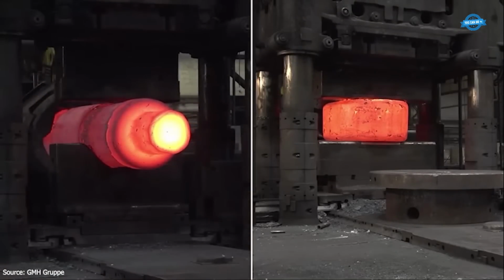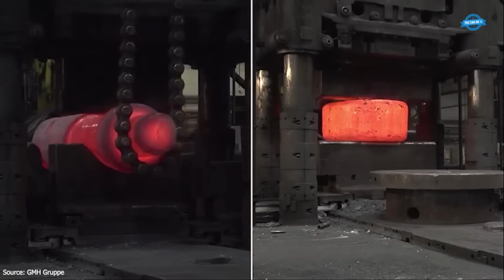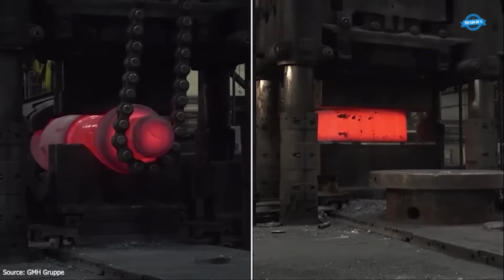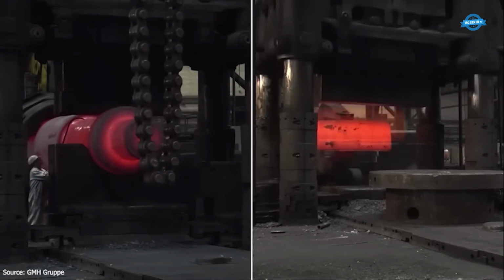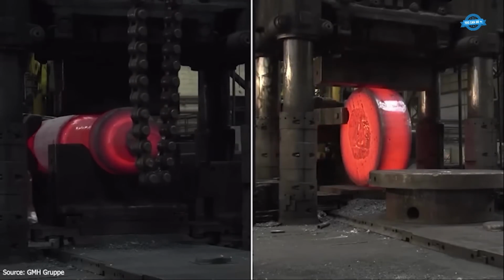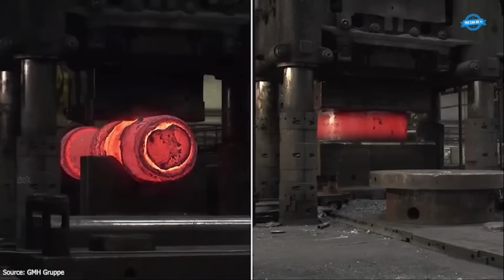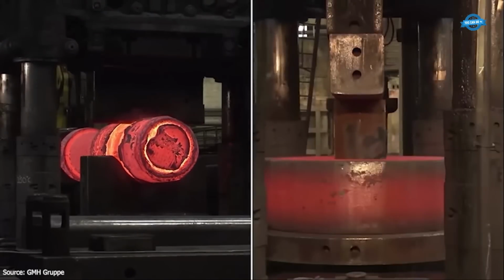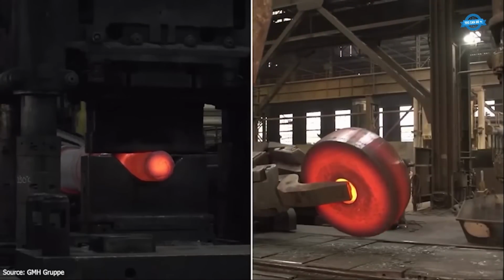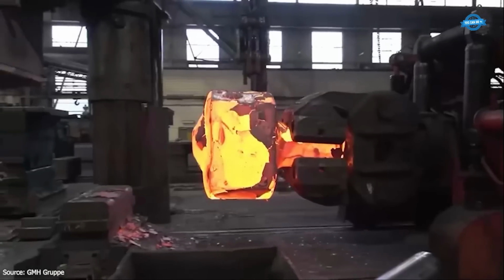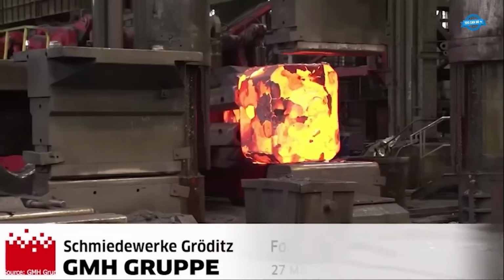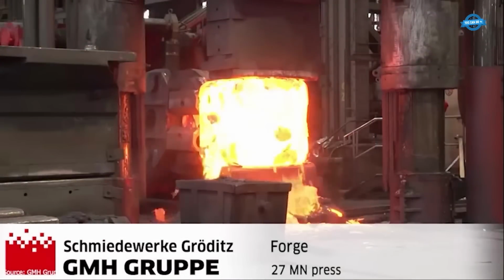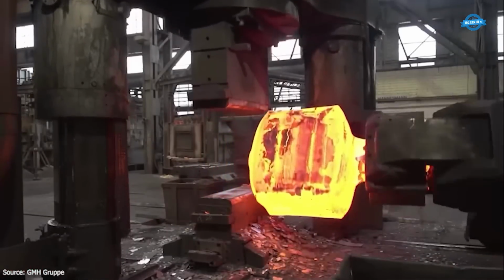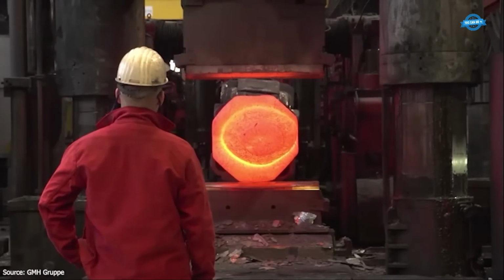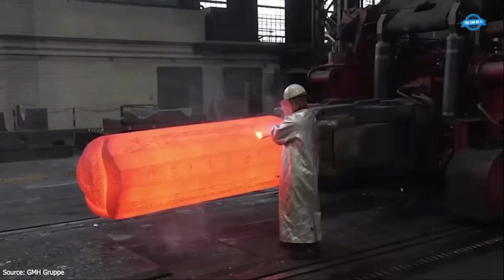Ingots are heated to 1,200 degrees Celsius and forged using a 60 meganewton press, supported by powerful manipulators. Power generation forgings like turbine shafts are upset after pre-forging for ideal material properties. For smaller forgings up to 20 tons, a 27 meganewton press is used.